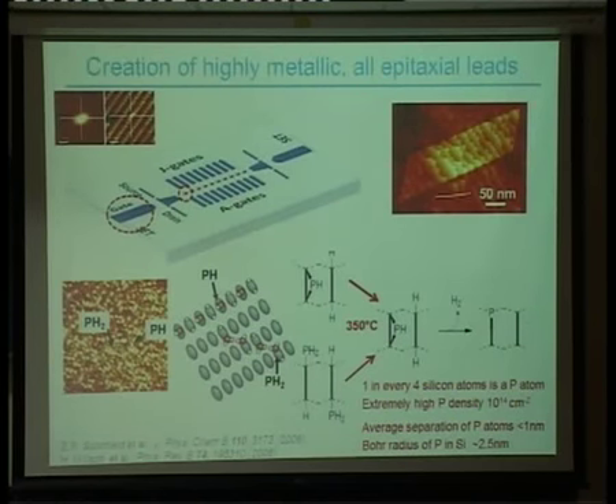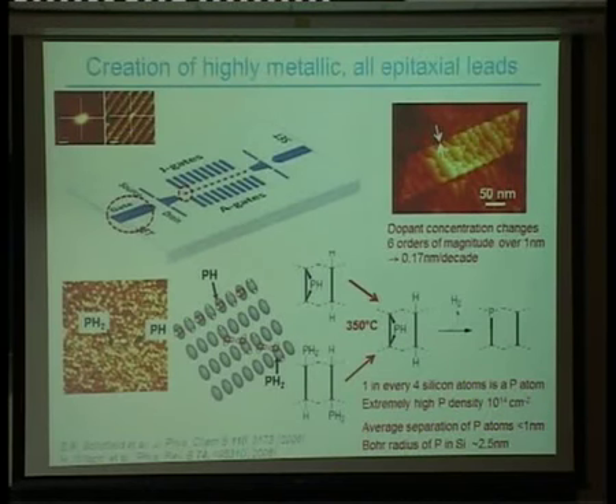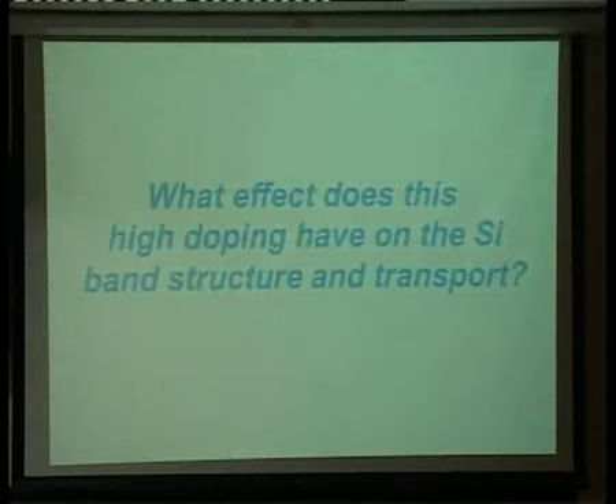So wherever we put these phosphorus atoms down at the high density, we create these local metallic states inside the semiconductor. And these metallic states are going to be used as our gates. So they're epitaxial gates, single crystalline gates that we bring in. The other interesting thing is in the same way that we've got very abrupt confinement in the vertical direction by dosing on one atomic plane, we also have very abrupt confinement in the lateral direction with the STM patterning. And this is something that, independent of the quantum computing project, the industry is very interested in for making ultra-shallow junctions, and that's another project that we have going in the group.